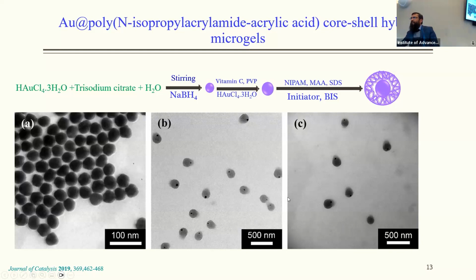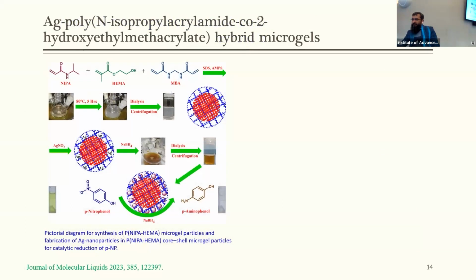The hybrid microgel system was characterized by transmission electron microscopy. You can see a single gold nanoparticle in the interior of the microgel system, and we have a cross-linked polymeric network around the single gold nanoparticle. We have used the single-step free radical precipitation polymerization method to obtain a poly(N-isopropylacrylamide-co-2-hydroxyethyl methacrylate) hybrid microgel system.